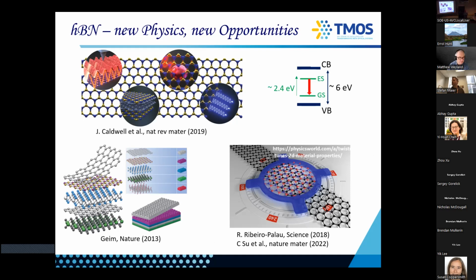So you can think of many, many different applications where you can just peel off your material that has the single photon source and put it wherever you like, for example, as a sensor or on your integrated photonic chip. And very recently, there was a lot of work on twistronics. And actually, there is also an effect even on the very deep defect within the HBN if you twist two HBN crystals, which is not intuitive, because from the superconducting work on graphene, you would think that it only influences the bands, right? But that actually doesn't. It also influences what's happening within your crystal itself with the very deep defects. So this was kind of the motivation when we started.